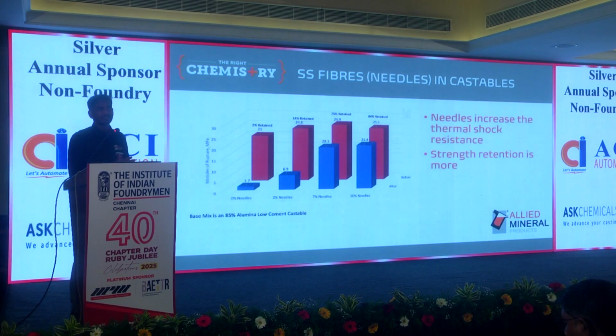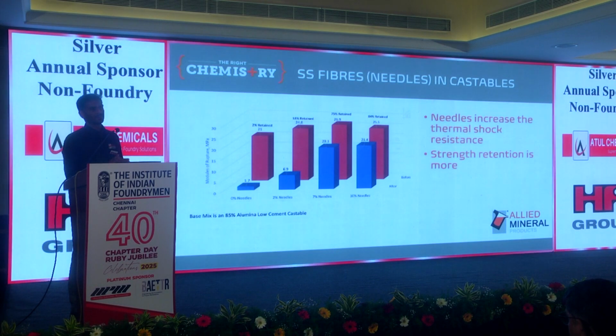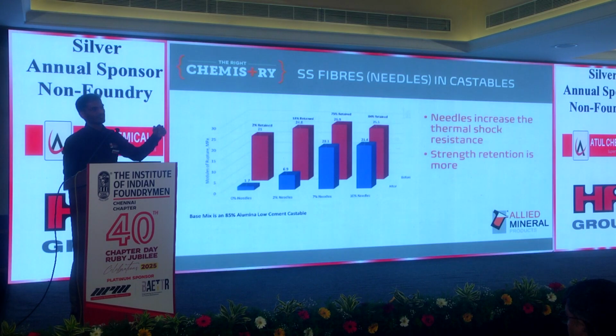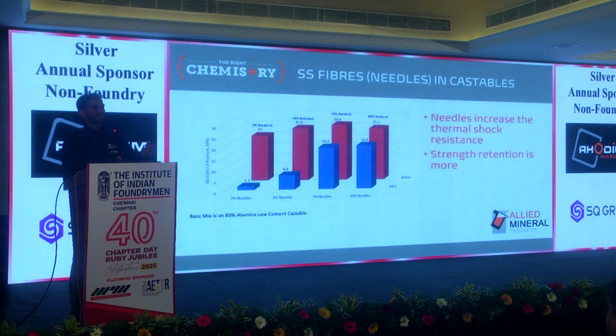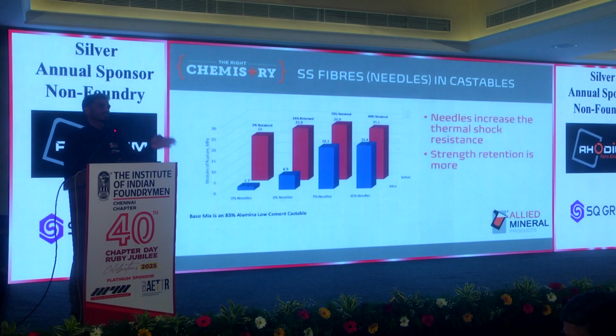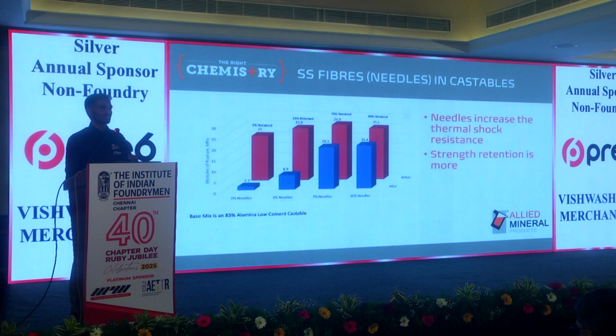Sir, whether we reduce the binder percentage with needles, or otherwise it will be kept more? No. Sir, as I said earlier, we select the castable based upon your operation. For example, I will most probably not choose any conventional castable for operations in the foundry industry. I will go with either low cement or ultra low cement castables. Now, if you have challenges of more thermal cycling of ladles, and you see more cracks in your system, then we add needles to hold those cracks without propagating further, so that your performance can be enhanced.